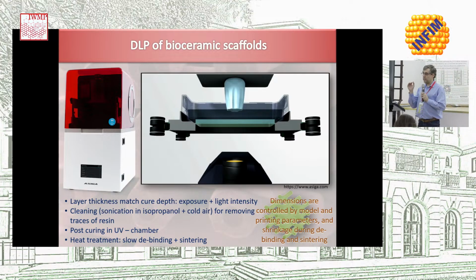The key here is to match the curing depth of the light, by adjusting the exposure and intensity of the light, so that the cure depth matches the layer thickness that you have selected. And if you do that, then you build your material layer by layer.